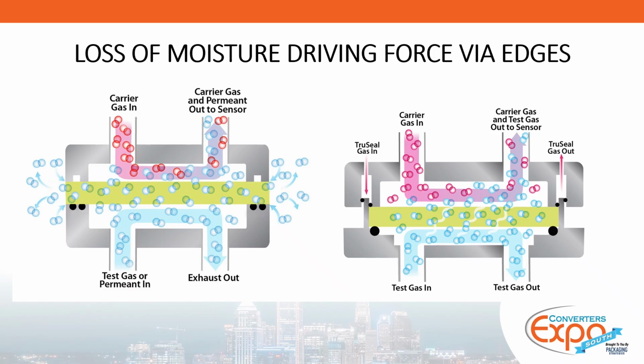Because that's another thing when testing these type of structures, depending on which lab you send it to. If it's not a controlled lab with the same relative humidity, at the time of year, you'll get different transmission rates because the ambient humidity is different. So you must always account for edge diffusion, or that has to be ruled out when you're designing these type of barriers. Okay, so